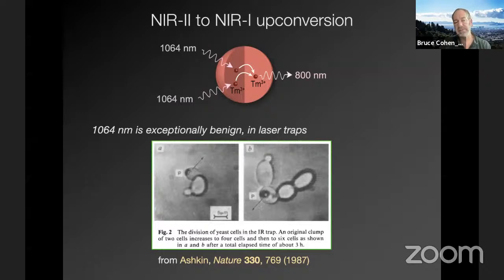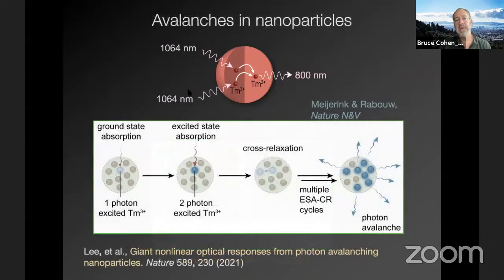There's not a water absorbance, so there's not really heating, and there's really nothing in the cell that absorbs well at 1064. And what we did was, this was sort of an accident, but it actually turned into a successful story, is showed that if we excite these lanthanides at 1064, we're able to get this avalanching process.